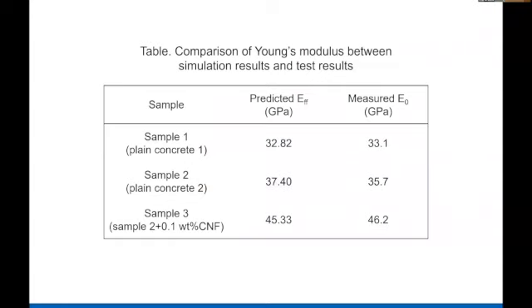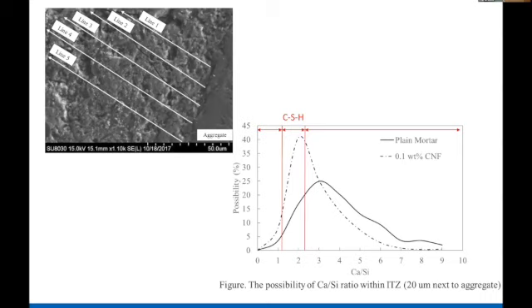So all three measured values and the predicted value, and you can see that the match is very good. The important thing to note is sample 1 and 2. Sample 2 had twice as many aggregates as sample 1, but the increase in modulus is not that much because of the weak interface. But sample 3, which had CNF, the modulus is substantially increased. Then we also did, and we are continuing to do, a study of, for example, the calcium to silica ratio in the interface with and without carbon nanofiber. And you can see the calcium to silica ratio is different. We have also shown that the size of calcium hydroxide crystals is smaller with CNF. So the addition of CNF fundamentally alters the material at the nanoscale, and this then increases the modulus.